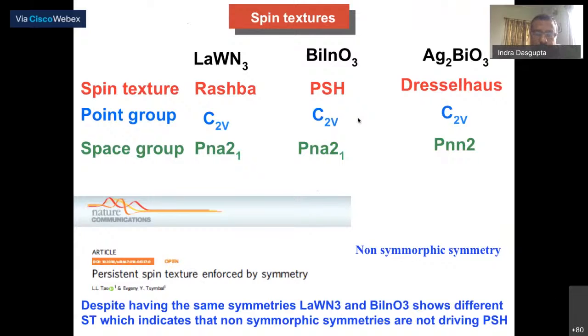So we can see the spin textures for these three compounds are different. Point groups are identical. Space groups are slightly different. Which implies that despite having the same symmetry, particularly LaWN3 and BiInO3, they show different spin textures, which indicates that it's not only the non-symmorphic symmetry or the crystal symmetry which decides the spin texture; there must be something else doing it. This is what we emphasize. For LaWN3, the predominant band character had been tungsten dx²-y². For bismuth indium oxide, it had been bismuth px. On the contrary, for Ag2BiO3 it happened to be bismuth s and oxygen pz.